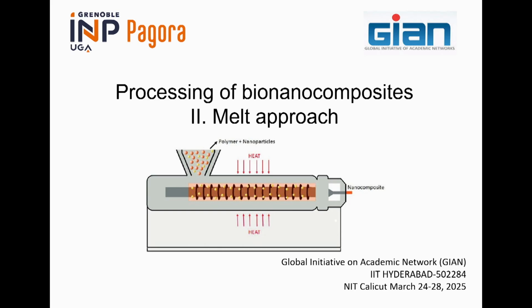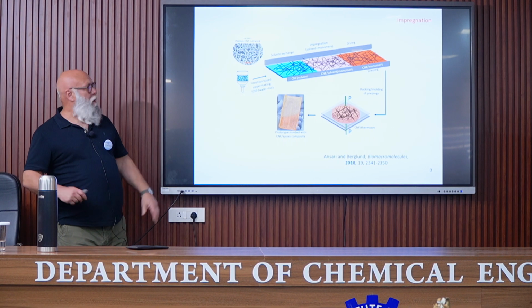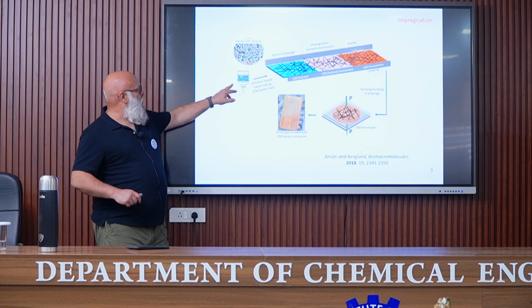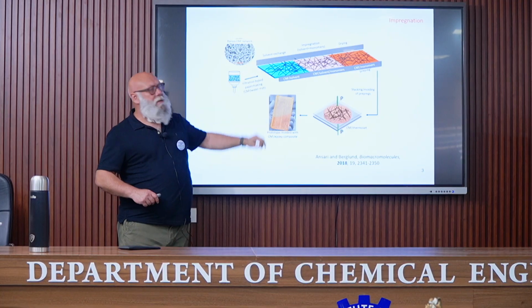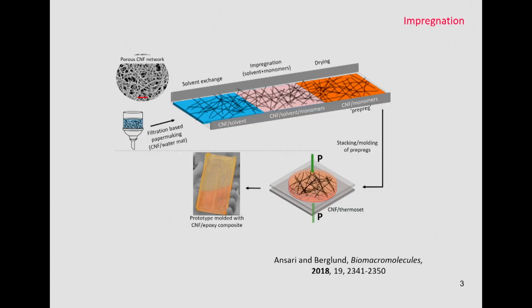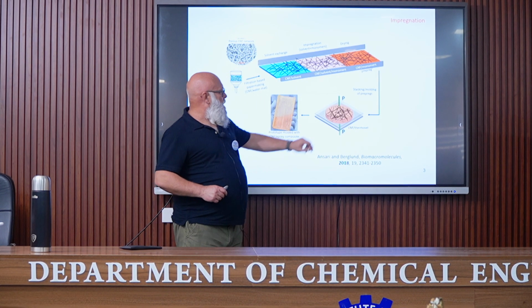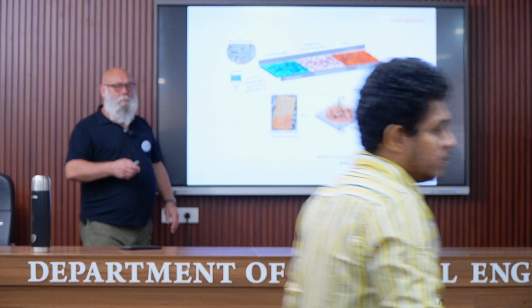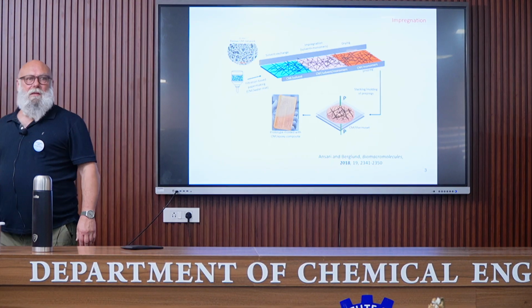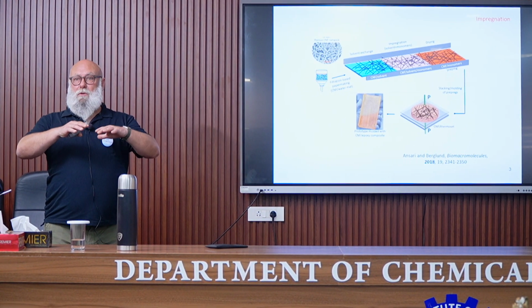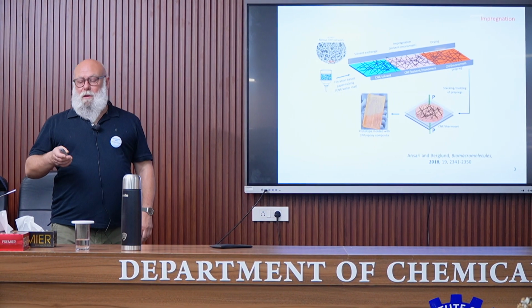Yes, impregnation. So it consists in forming a mat of cellulose nanofibrils, like nano paper if you want. And then this mat that contains some water can be solvent exchanged to a solvent, of course, that can dissolve the polymer that will be used, and then can be impregnated. In this case, it was with a solvent and monomer, so it was a thermoset polymer that was polymerized in situ. Then it was dried and hot pressed to obtain a composite. Of course, in this case, the cellulose content is quite higher because we start from a mat with a given porosity, and the porosity is filled with the polymer.